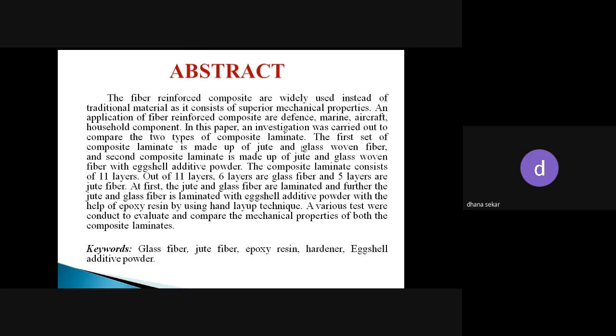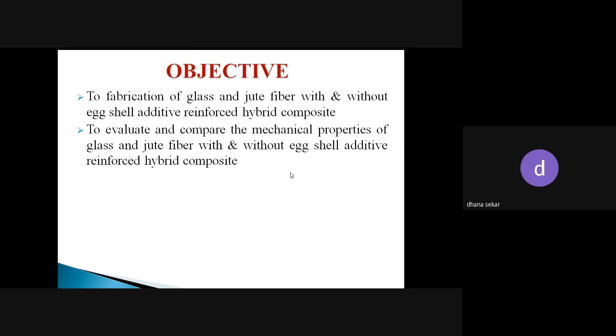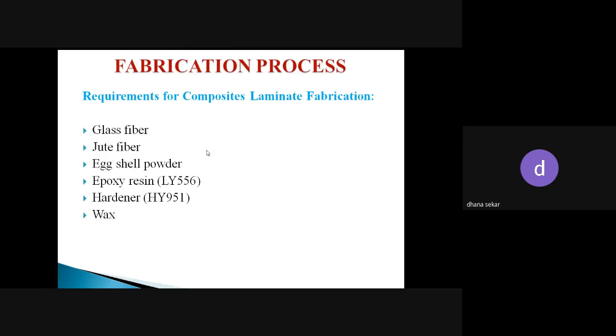After that, we conducted a mechanical test for both the laminates, and we compared and evaluated both the laminates. So the objective is, first, we fabricated the glass and jute fiber reinforced hybrid composite and the glass and jute fiber with eggshell additive reinforced hybrid composite. After that, we evaluated and compared the mechanical properties of glass and jute fiber with and without eggshell additive reinforced hybrid composite.